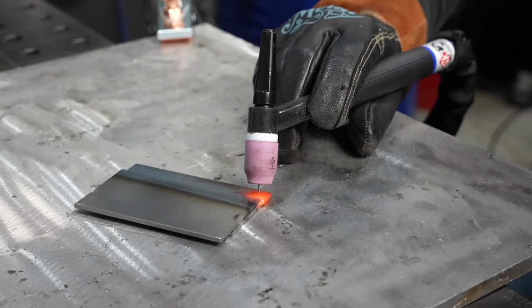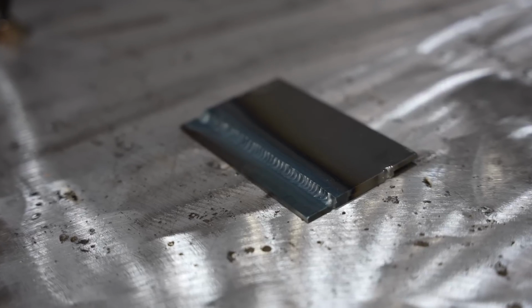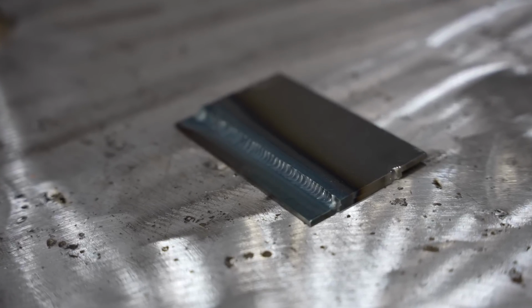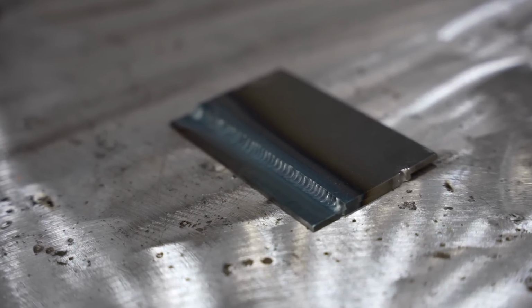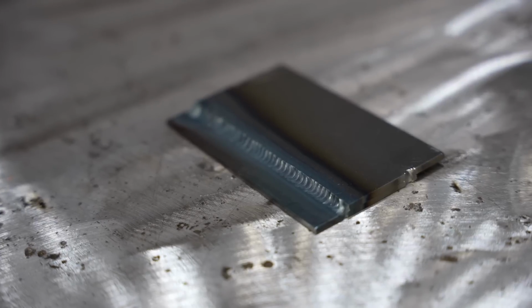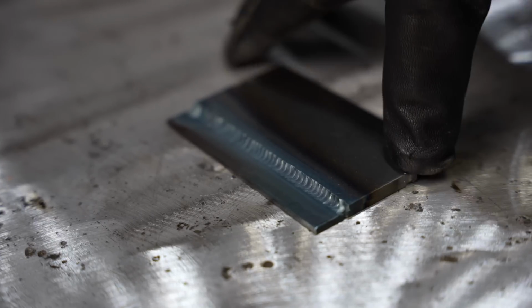So I keep dabbing along, and in the end it came out with something that looks pretty good for a weld on steel. You're going to typically have some gray oxidation like this no matter what you do, and if you used a huge cup, you could avoid some of that. And honestly, if I used a little bit more amperage and welded faster, it would probably reduce it a little bit, but it's certainly acceptable.